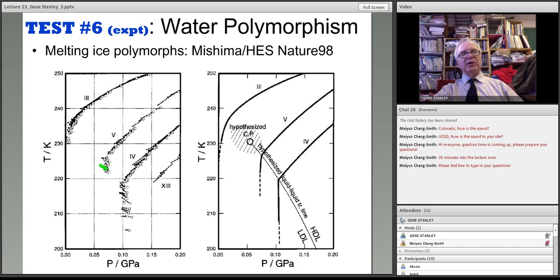And what do you see here? You see that at low temperature there's a well-defined kink, and by the Clausius-Clapeyron relation, that means we're in one phase here and another phase here. The high-pressure phase is obviously the high-density liquid, because pressure always induces an increase in density. And the low pressure phase is the low density liquid.